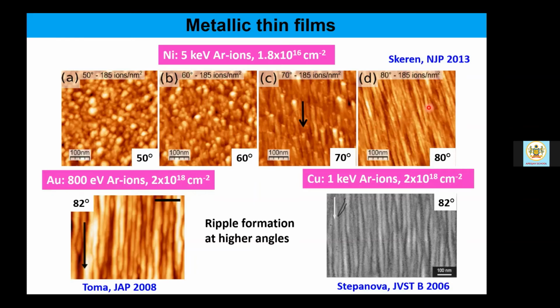And by using ion energy of 800 eV argon and with 2 orders of higher magnitude at an angle of incidence of 82 degree. Again, some other group had reported the ripple formation at 82 degrees, and using copper ion also. This was not for nickel, this was for gold, and this is for copper.